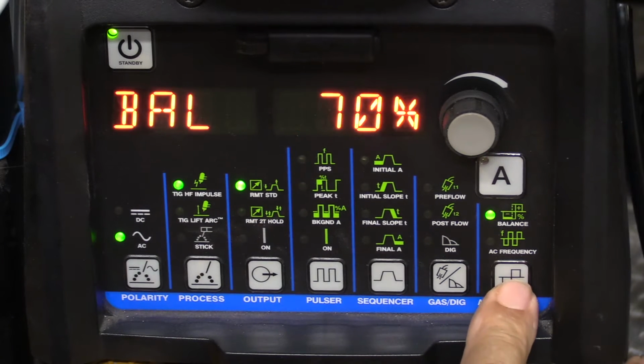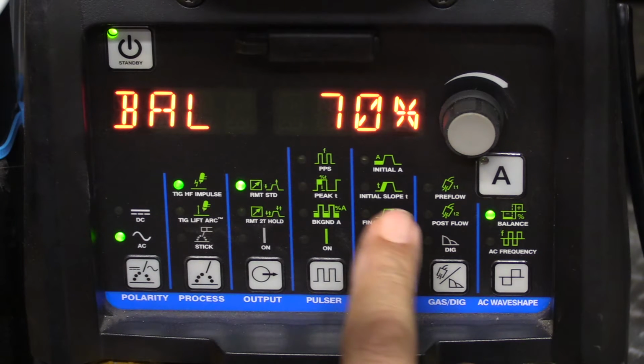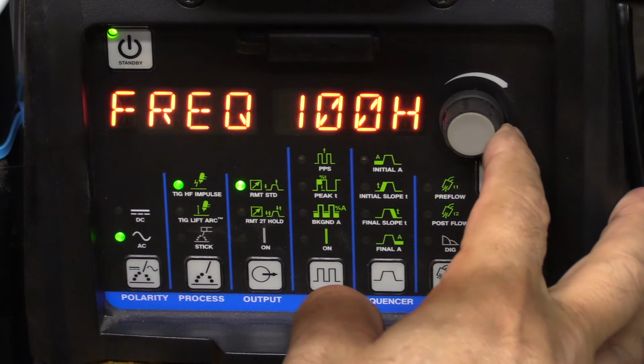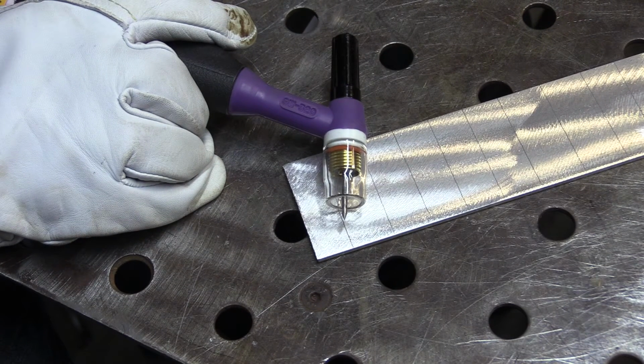I won't always be full 130, but that's what the machine is set at. Balance to 70% or 30% cleaning. If you have AC frequency adjustment, 100 hertz is a good place to start. I'll be sticking my electrode out a little further than I recommend, just for the purposes of filming. Rule of thumb on electrodes stick out no more than the inside diameter of the cup, but enough where you can see the tip of the electrode, and there are always exceptions to that rule.